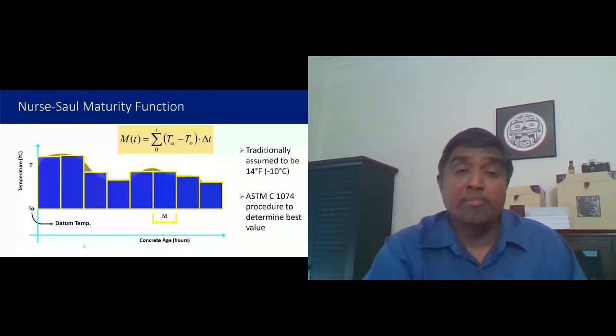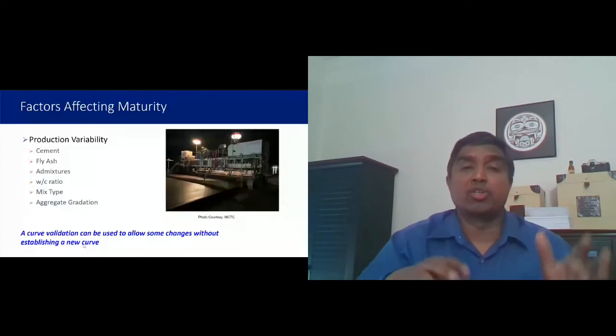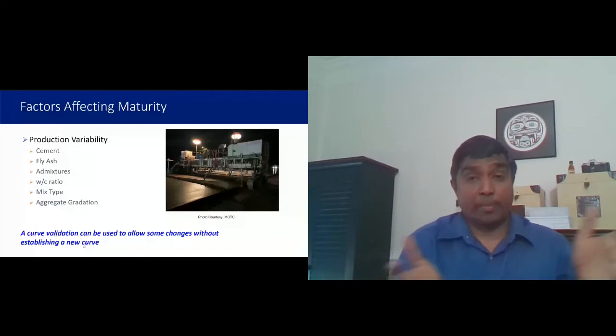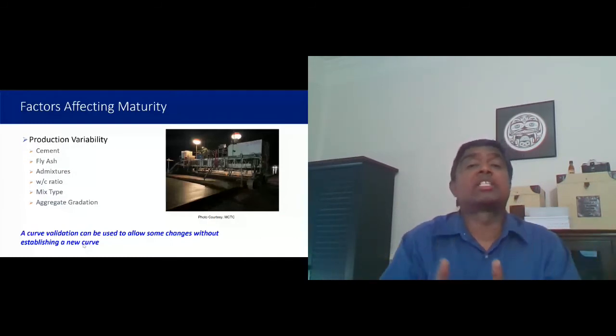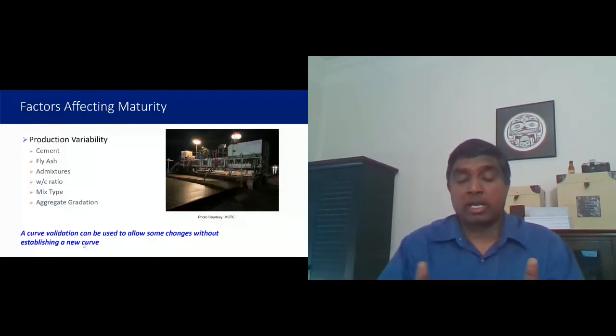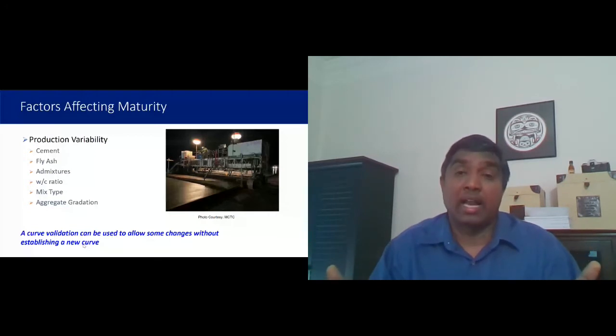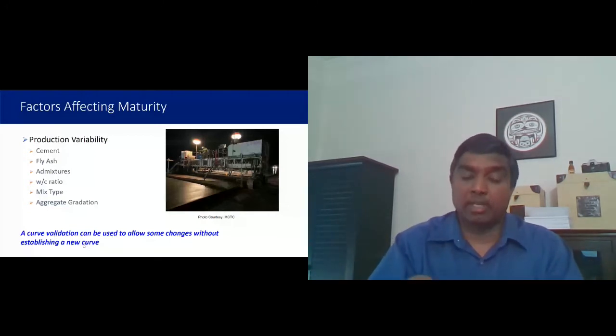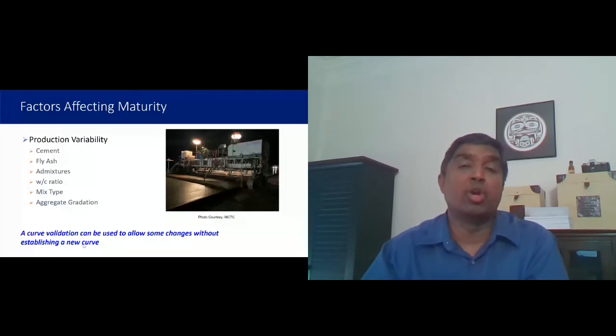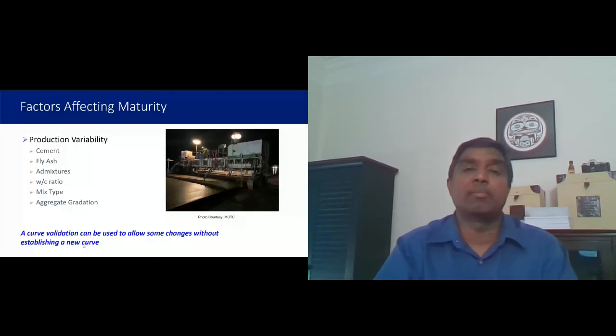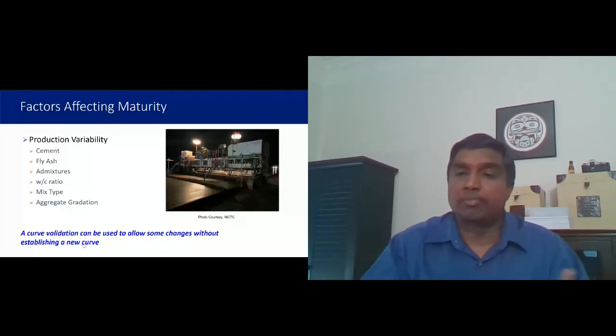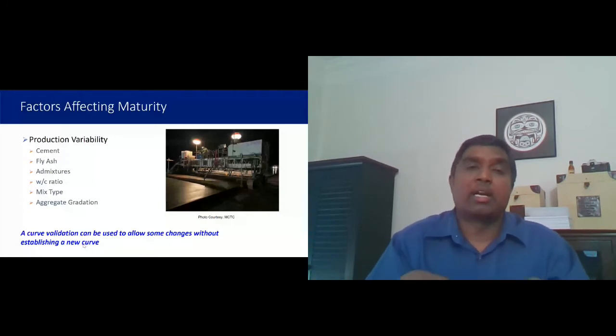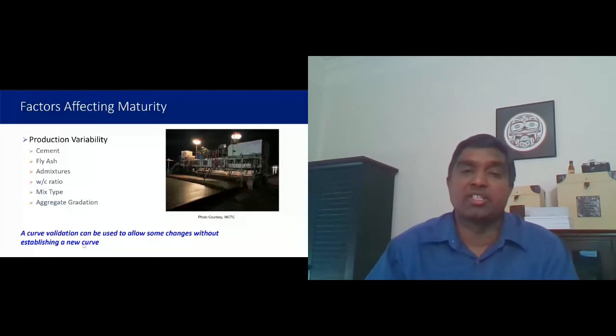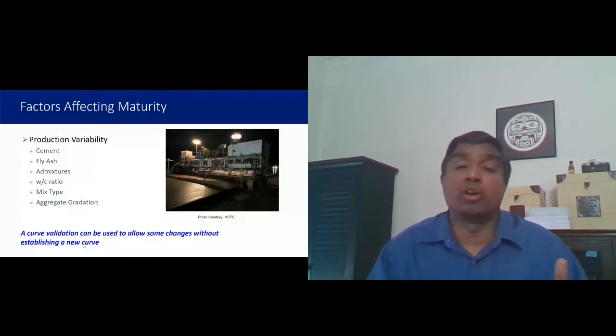So in terms of verification, if you remember, we've talked about the calibration curve, right? So you prepare a calibration curve at the very beginning of a project, and then you use that calibration curve to estimate your compressive or flexural strength throughout the project. Now, how long is that calibration curve valid? The important thing with maturity is the calibration curve is valid as long as your mixture proportions do not change significantly. When I say significantly, typical production variability is okay, but let's say your cement source changes, or your fly ash content changes, or your water content changes significantly. Well, if those things have changed, then you have to redo your calibration curve.